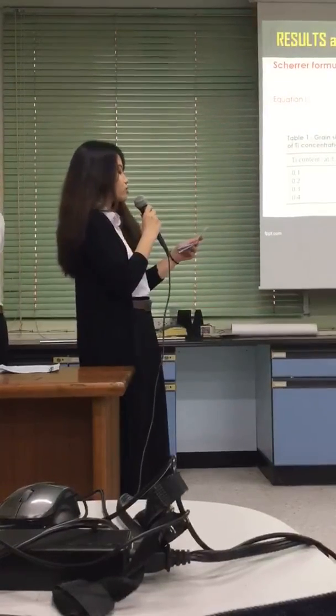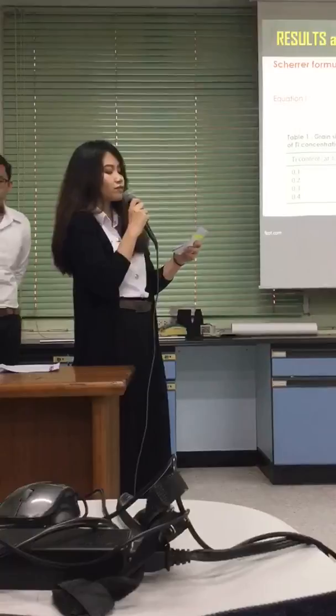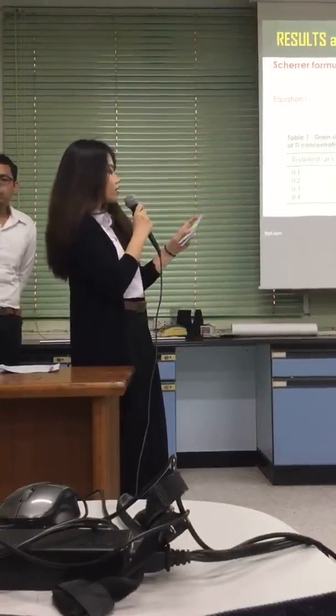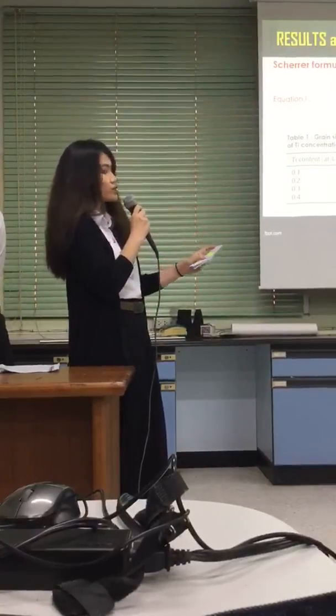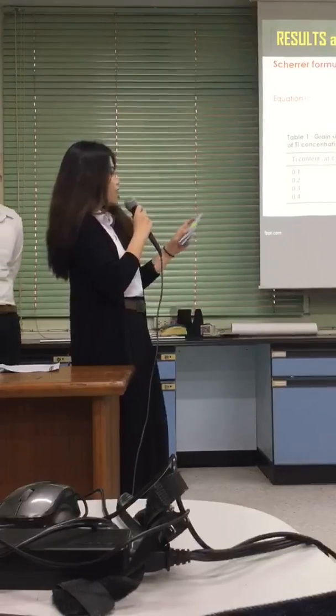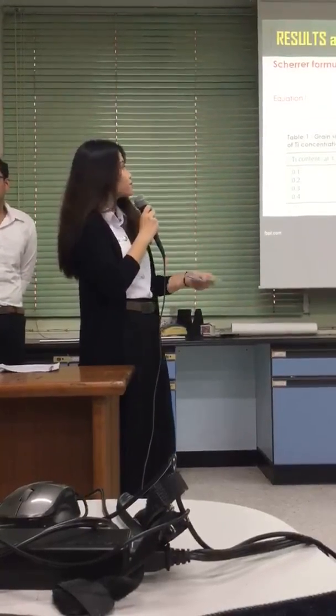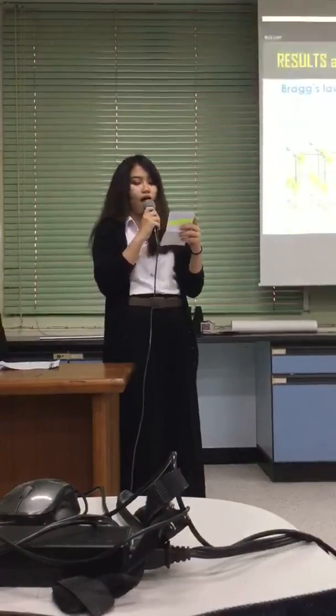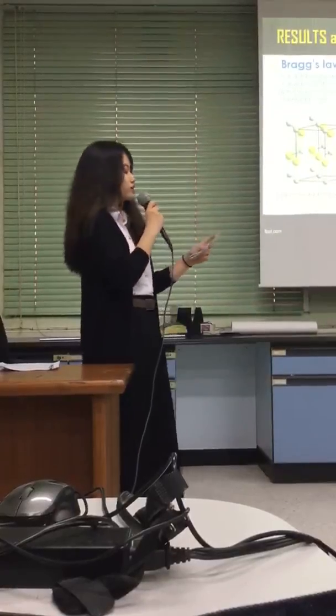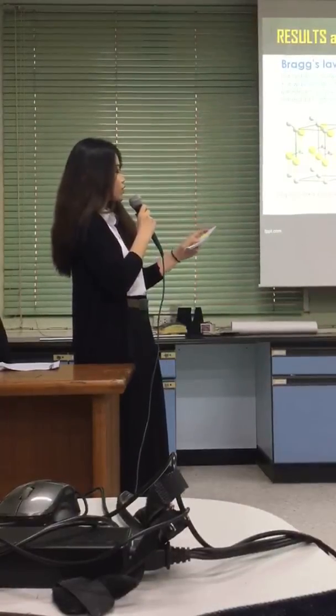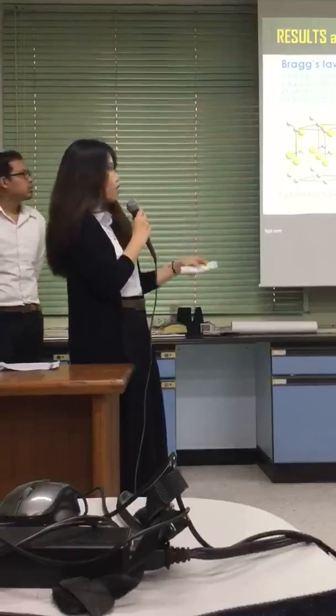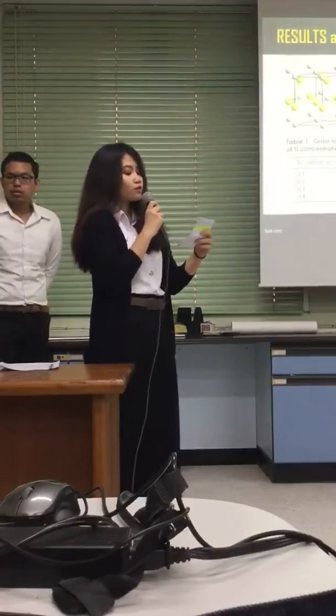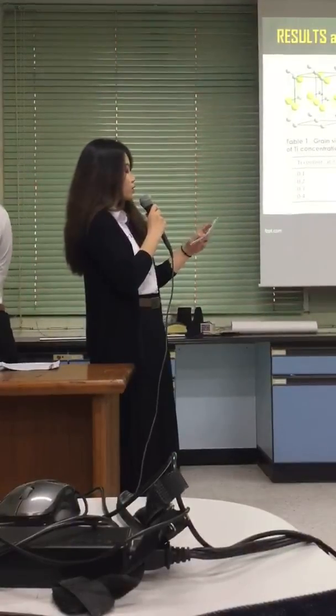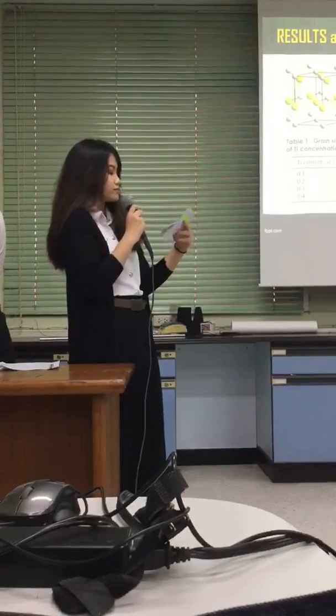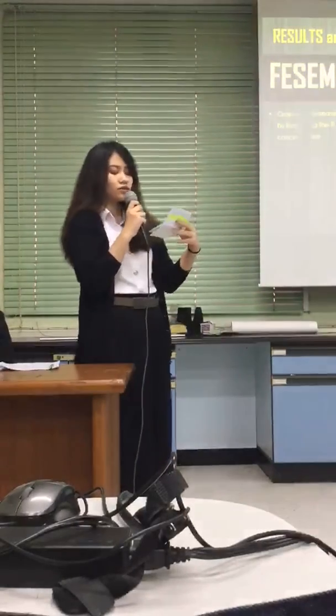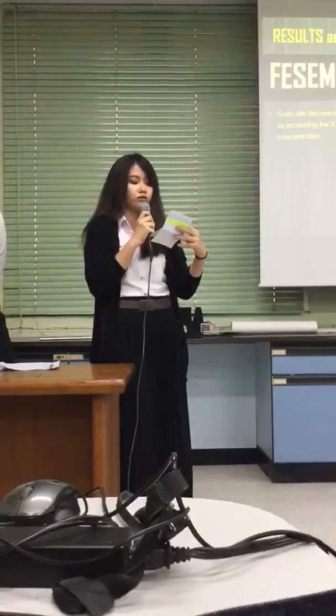Using the Scherrer formula to calculate the crystal size of samples, shown in Table 1, we found that the crystal size decreased upon titanium increase. As for lattice parameter, the samples are hexagonal wurtzite structure, using Bragg's law with equation 3 to calculate it. Shown in Table 1, lattice parameters a and c decrease upon titanium increase too. The next is result from FESEM technique.